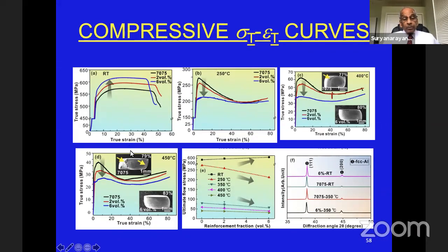But if you now come to 450 degrees Celsius, for example, the aluminum 7075 is on the top. That means it has a higher strength than the composite. And that is something which is interesting. And if you plot the ultimate flow stress as a function of the volume fraction of the reinforcement, you can see at different temperatures, there is a reversal that is taking place.